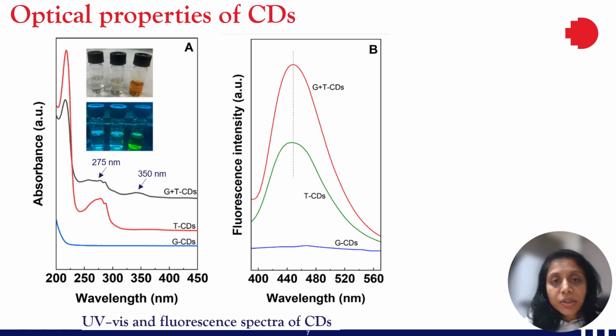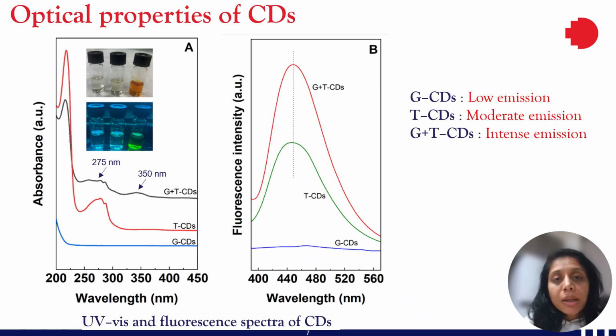And if we see the fluorescent spectra, the glutamic acid and tryptophan carbon dots exhibited intense emission bands centered at around 450 nanometer, while the tryptophan carbon dots showed moderate emission. Conversely, glutamic acid carbon dots demonstrated lowered emission when compared to both other carbon dots. So with this, we can infer that carbon dot formation occurs preferentially from tryptophan rather than glutamic acid.